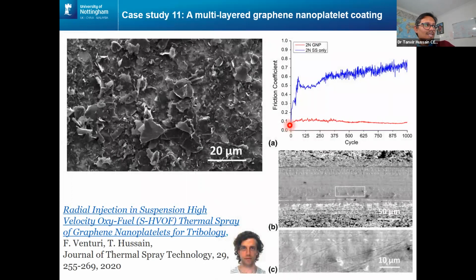We did succeed in depositing a loosely bonded GNP film. And with that film, this is the coefficient of friction versus number of cycles. We can bring the coefficient of friction down to 0.1 here, compared to 0.6, which is typical. So it does work quite nicely as a self-lubricating material.